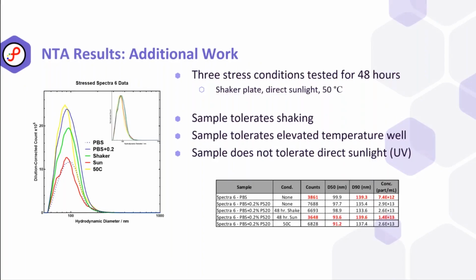What we did do, however, was some stress work. So we looked at three common stress conditions. First, a shaker plate. We just put a vial of this material with the PS20 on a shaker plate and shook it for 48 hours. It's a pretty easy way to aggregate most therapeutics. 50 degrees C, so accelerated stability, was a second condition. And then we did have it in direct sunlight for 2 days. So that's probably more like 24 hours or so of direct UV irradiation.